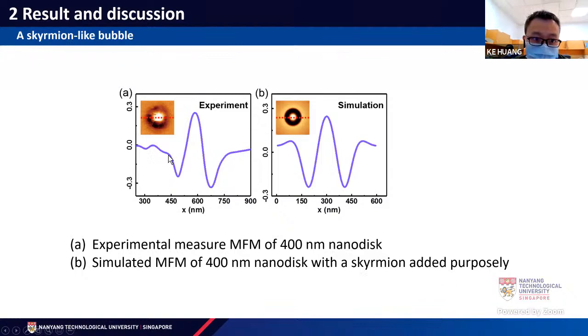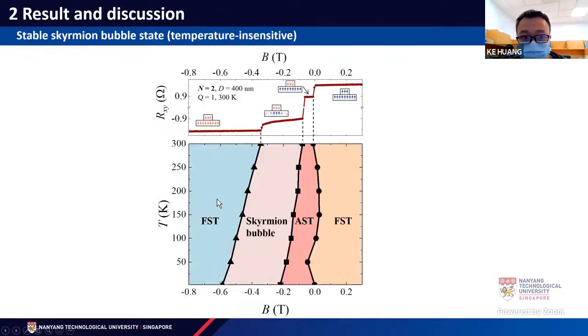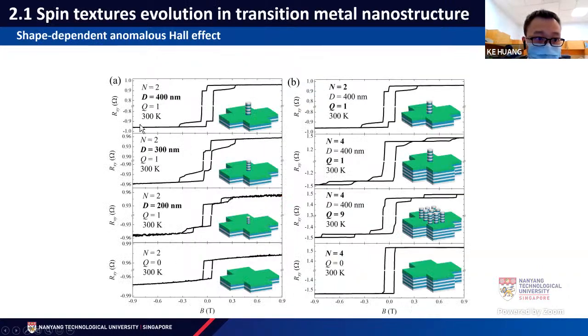And we checked and we find that these two MFM signals across this line are very similar. So we would like to propose that the spin texture of our bubble is actually the skyrmion bubble. So what we further do is we measure the anomalous Hall effect at different temperatures, and we found this skyrmion bubble region is very stable. It has little change from 300 K to the base temperature. It had no change. It's very robust.